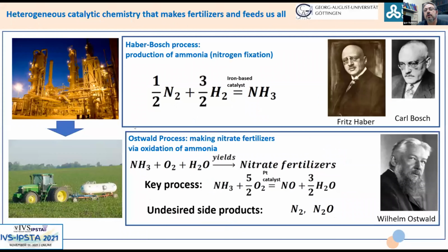So let's look at two important industrial processes that literally put food on our table. We're talking about Haber-Bosch, which is about fixation of nitrogen, producing ammonia, and the perhaps less known subsequent process called the Ostwald process, where ammonia is converted to nitrate fertilizers, while the key reaction behind this process is oxidation of ammonia by oxygen over a platinum catalyst to produce nitrogen oxide. It can also yield undesired side products such as N2, which reduces the efficiency of the process, and also N2O, which is quite harmful since it has a greenhouse effect and also leads to ozone depletion.